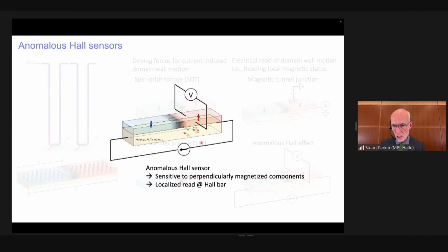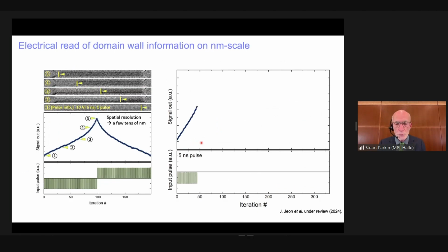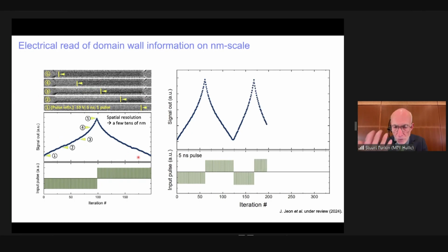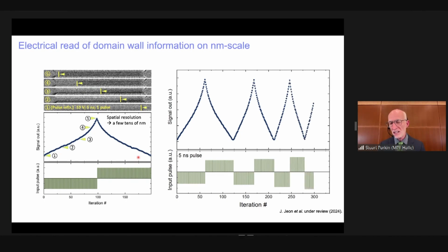And this Hall voltage enables us to detect the orientation of the magnetization or the domain walls. And now we've demonstrated that we can now shrink the width of the racetrack from microns, which is necessary for optical detection, to less than 80 nanometers. And these types of dimensions are relevant technologically. And in this picture, you can see a racetrack. First, we show the optical image on the top left, a single domain wall moving from the right to the left. And then we follow this domain wall moving through this racetrack all the way from one side to the other using a set of Hall bar sensors we've lithographically patterned into the racetrack, which is 80 nanometers wide.